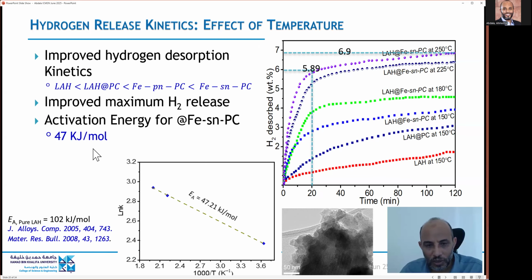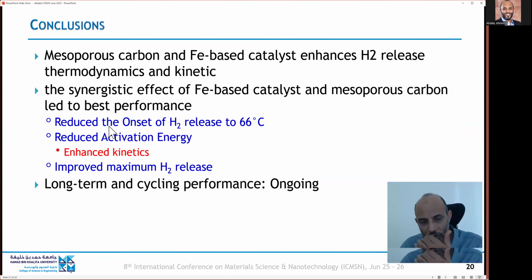So we were able to reduce the onset temperature to 66 degrees compared to 150. We reduced the activation energy by 50%, which significantly improved the kinetics, and we improved the maximum hydrogen release at fixed time and fixed temperature. Currently, we're looking at the other critical element, which is the long-term cyclability performance, and we hope to update you on that soon.